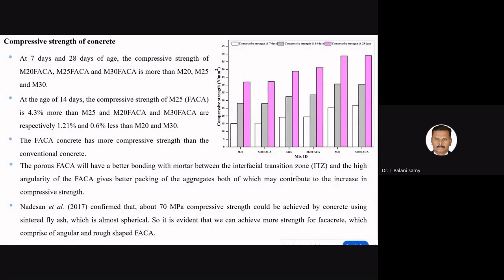These are the compressive strengths. I don't want to go into much detail about it. What we observed is that the concrete strength is increasing, which is good. What is the reason? What is the mechanism behind this? That is what we want to take care of. For FACA, I have given the advantages here. The FACA will have better bonding with the mortar in the interfacial transition zone, ITZ, and the high angularity of FACA gives better packing of the aggregate, both of which may contribute to the increase in compressive strength.